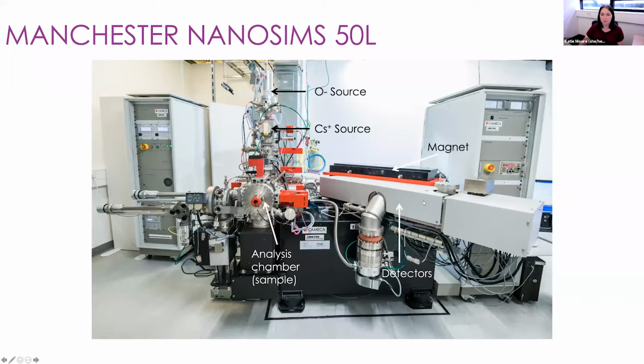Now, it's worth noting that the NanoSIMS operates under an ultra-high vacuum at about 10 to the minus 10 millibars. That's much higher than you'd expect to get in an SEM or TEM. Because of that, we have quite a lot of pumping capacity at the start here. We have the airlock here where we introduce our samples into the NanoSIMS. We then have a storage chamber just here, and the analysis chamber is just here.